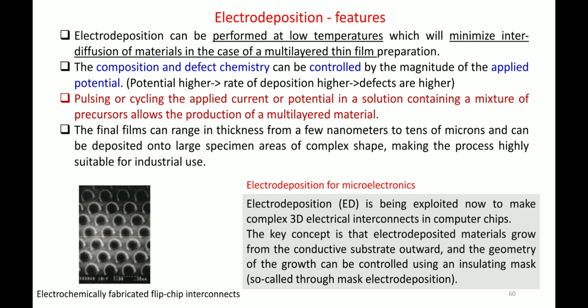As an example, you can see there is electrodeposition for microelectronics. The electrodeposition is being exploited now to make complex 3D electrical interconnects in computer chips. So suppose there are computer chips and you just want to deposit certain material in certain areas of the chips, and the size and shape of the chip is very complex. In that case, the electrodeposited materials grow from the conductive substrate outward, and the geometry of the growth can be controlled using an insulating mask, so-called through-mask electrodeposition.